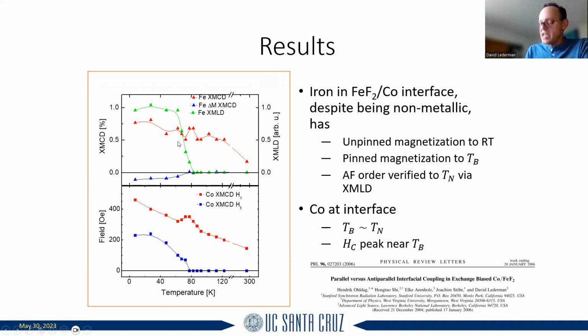set of data, and you can see here that in green we have the linear dichroism due to the iron in the iron fluoride. You can see that this tracks really well the transition of the antiferromagnet. Here it goes to 0 at the Néel temperature, which for these films is a little bit above 80 Kelvin, and then it stays 0 here.